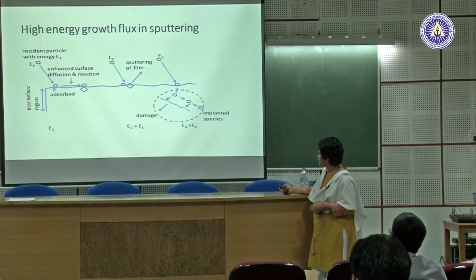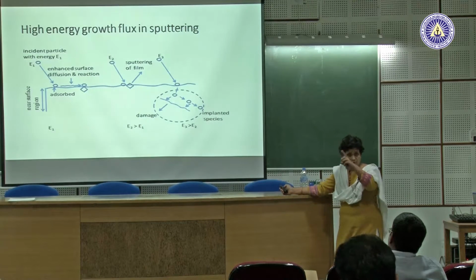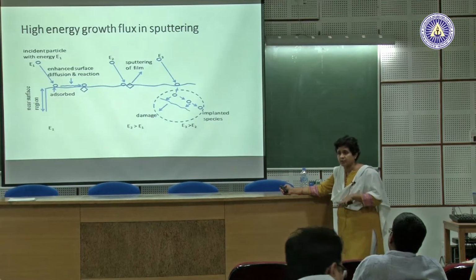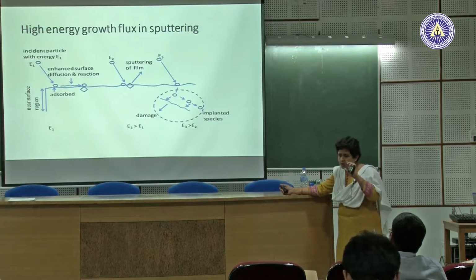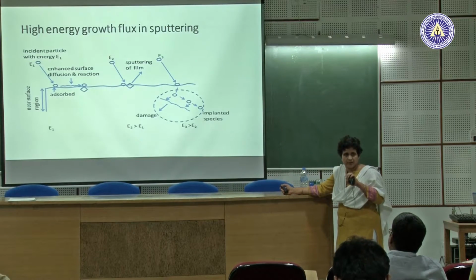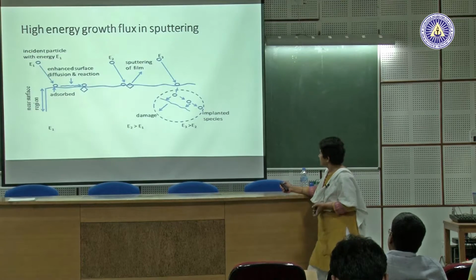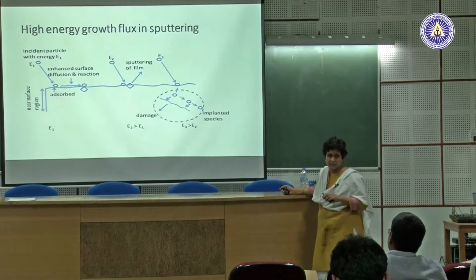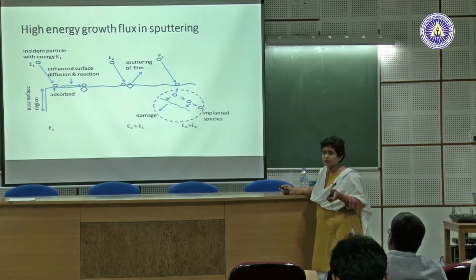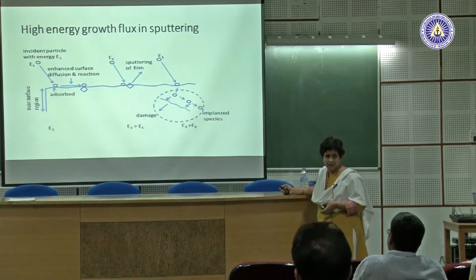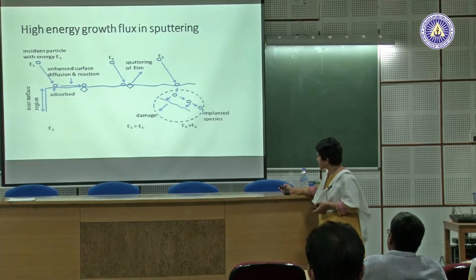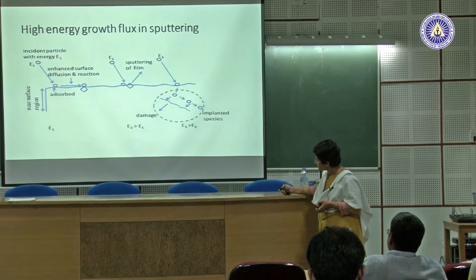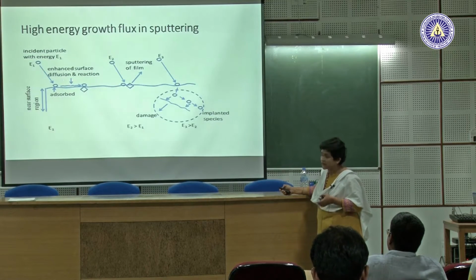what is different here, from the point of view of what is happening on the substrate, why sputtering is considered good, especially for hard coatings, because you want a good adhesion to the substrate for hard coatings and other things. So, the difference here is that the atoms which are coming, compared to the evaporation, they are coming at a much higher energy, right. Few hundreds of volts, you are accelerating argon ion at a few hundreds of volts, it sputters an atom, the atom which is coming out is at a much higher than the thermal energy at that temperature. Okay. So, atoms are coming at a much higher energy, because of that energy, they have an enhanced surface diffusion.